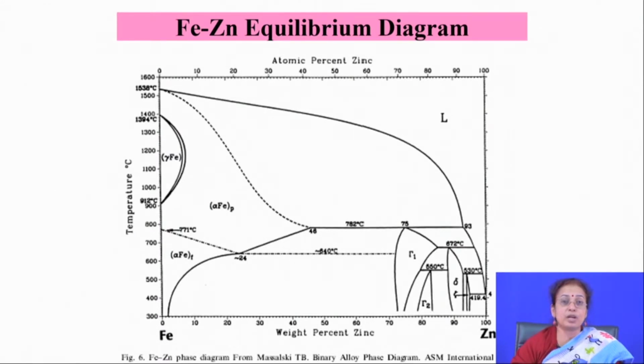If you talk about a pure zinc coating, and you just quickly go through the iron zinc interface, you will find that this is a zinc rich corner, because usually when you dip an iron based component in molten zinc, there is dissolution of iron from the surface, and that dissolved iron mixes with zinc and then forms different intermetallics.